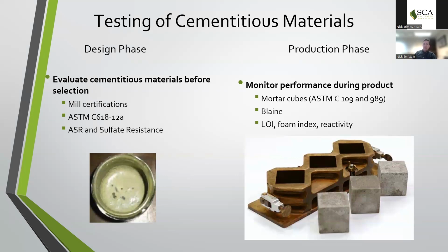During the production phase, maintaining the high quality of those supply lines is usually done through assessment of the raw materials. Very common tests that we will see, most everyone knows about, just continuing to maintain gradations and running moistures, which we'll talk a little bit more about, but also on the mortar-based side, performing cubes, performing Blaine, and then particularly if you're using fly ash, checking for LOI, foam index, and reactivity, so you can accurately adjust your mix design should there be an increase or drop off in performance of any of those raw materials.